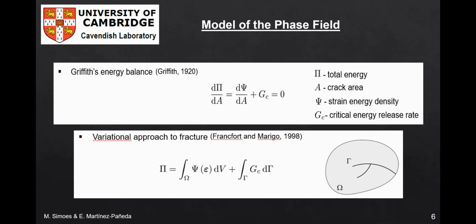So at this point, you might say, okay, all good on the computational side, no issues dealing with evolving interfaces such as cracks. But when do those cracks propagate? Or in other words, what differential equation do you use to evolve the phase field? Well, one of the nice things about phase field models is that they provide a computational framework for Griffith's energy balance. Griffith, one of the fathers of fracture mechanics, postulated that a crack would grow if the energy released by the solid reached the critical value, the so-called critical energy release rate or material toughness, GC.